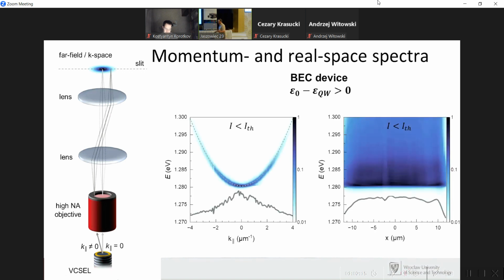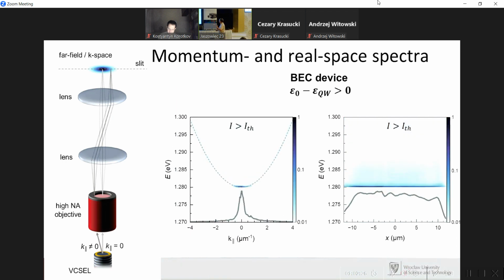So below condensation threshold in our BEC device with a specific tuning, we see thermalized distribution, homogeneous emission from the laser, nothing surprising. But above the threshold, we see collapse to the ground mode, which is homogeneous over the whole large area VCSEL, 23 microns.